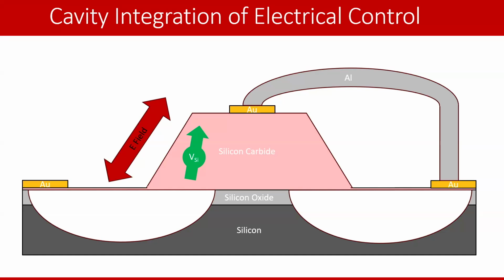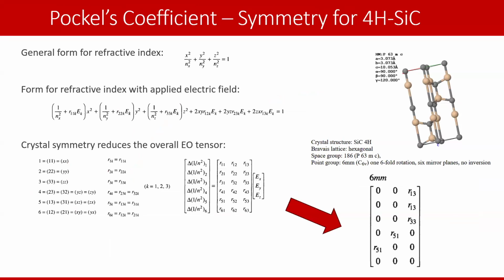But making these devices, the material that we use to host the defects, the silicon carbide, is relatively rare. We get it from one specific guy in Sweden, a collaborator of ours. As a result, all this testing to make this harebrained electrical optical device together should be done ideally with silicon carbide that's not as rare, with materials that I can spend a lot of time in the fab ruining and have it not be a problem. And so it turns out that, very conveniently, this electric field orientation that will tune your defects is also the same electric field orientation that applies the electro-optic tuning of silicon carbide itself. This is along the extraordinary axis of C-plane silicon carbide.